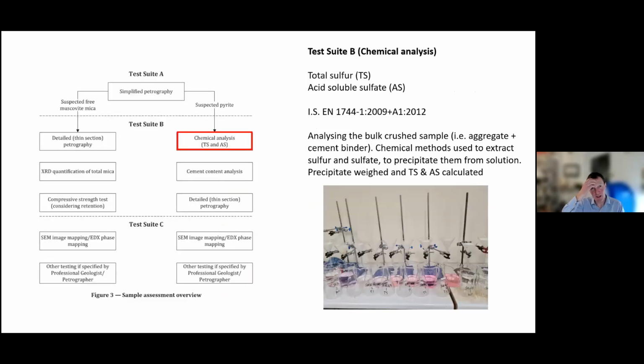in compressive strength. Then for the pyrite pathway, chemical testing was favored. So there's total sulfur and acid-soluble sulfate to another European standard. And this is analyzing the bulk crushed concrete. So it's the aggregate and the cement binder and any additives that might be in there. And effectively, chemical methods are used to extract the sulfur and sulfate, two different methods, and then precipitate them from solution. And this precipitate is weighed, and from that, total sulfur and acid-soluble sulfate is calculated.